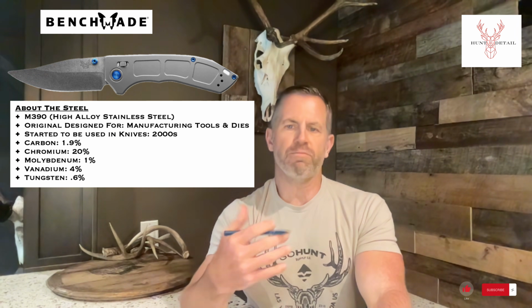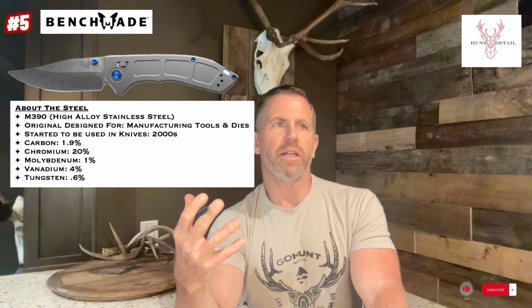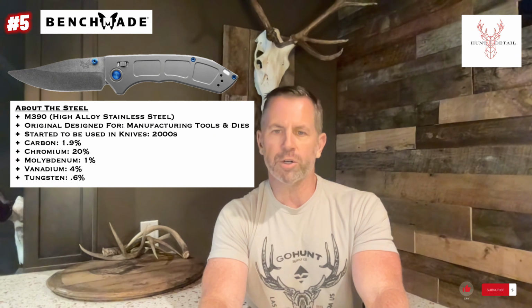Now, coming in at number 5, we have the Benchmade Narrows Titanium. This is made out of M390 stainless steel. That steel came out in the early 2000s, originally for molds and dies. It is a high alloy stainless steel. And this is really interesting. Now we're at 20% chromium, 1.9% carbon, and then traces of tungsten, vanadium, and molybdenum.